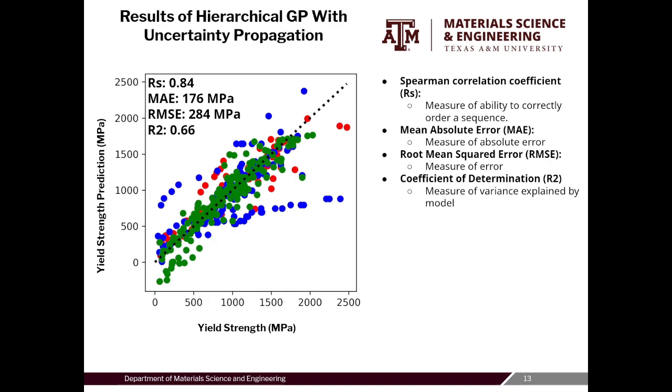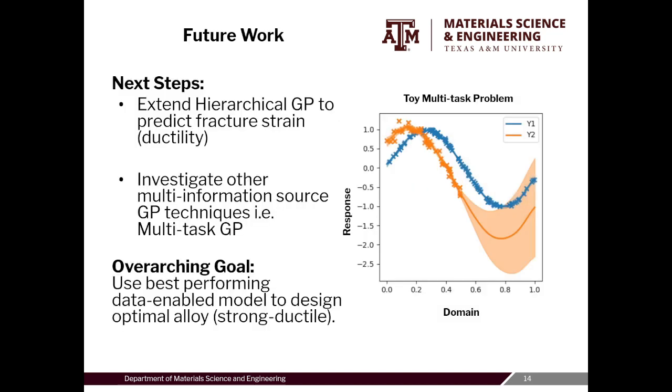And here are the results of the same model, but with uncertainty propagated through the usage of sampling functions and training many yield strength GPs. We use the same 3 folds and sample the functions of the hardness GP 5 times, generating 5 yield strength GPs with a 3-fold split and averaging their outputs. We see that all the metrics recorded have improved, indicating that propagating the uncertainty is a benefit and increases the accuracy of the model.